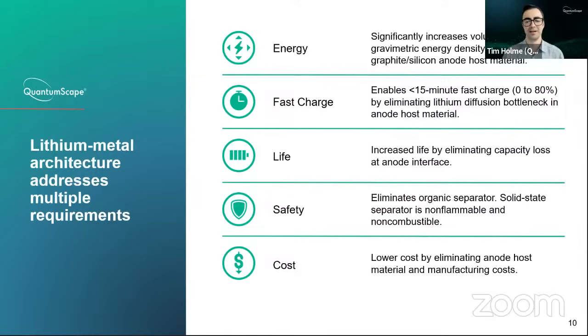In terms of safety, by eliminating some of the flammable components and the organic separator that could melt and separate and expose more contact between anode and cathode in a thermal runaway event, you can replace it with a solid that's stable to very high temperatures and doesn't melt in most conditions. And then in terms of cost, you can also eliminate a whole set of manufacturing steps and a whole set of materials from the bill of materials of the battery. So these are five of the real key metrics of interest to batteries and especially to an EV, and all of them could be meaningfully improved, we believe, with a lithium metal anode.